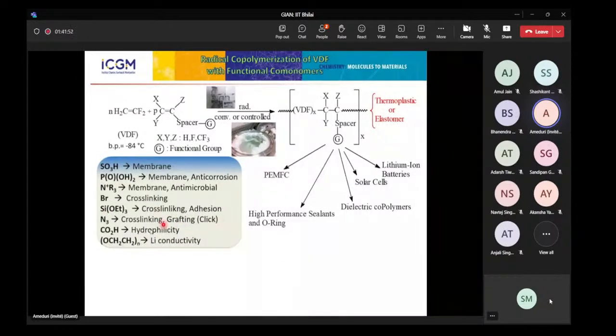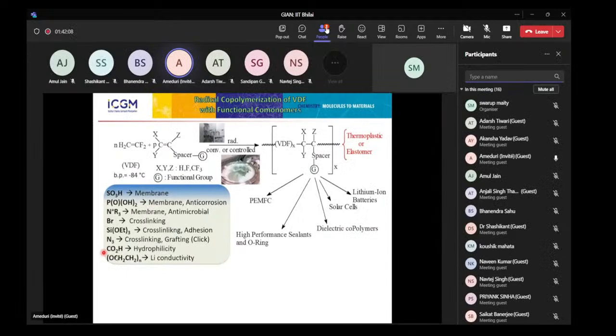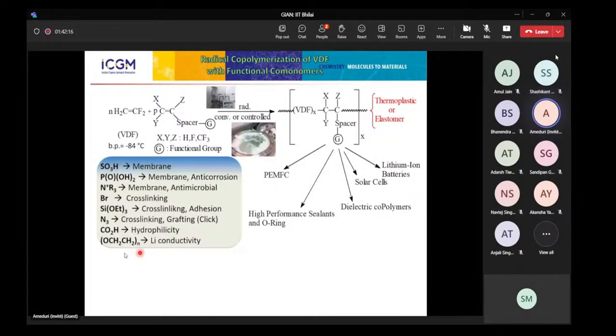You can also think that PVDF is hydrophobic. It's not very hydrophobic, but for membrane filtration and water desalination, it's good to have some hydrophilic channels. And by using some carboxylic acid or PEG substituents, you can induce some hydrophilicity, and in the case of PEG, you can have some lithium conductivity because you have coordination of the lithium by the oxygen of the PEG. So the idea is, if you are able to manage this group in your PVDF, you can have a function, for proton exchange membrane fuel cells, or even cross-linking to get high performance sealants or O-rings, directly copolymers with a high amount of VDF. Of course, for solar cells, we put some phthalocyanine, for instance, or even for lithium-ion batteries in the case of PEG or cyclocarbonate.